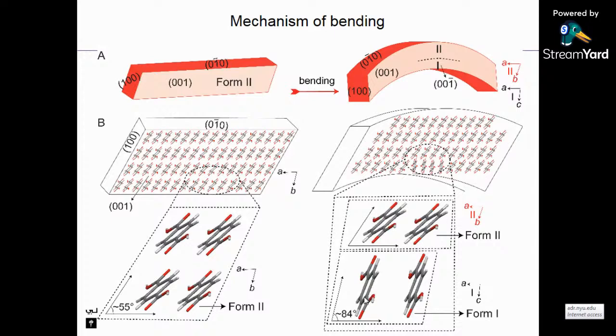So due to this existence of polymorphs at the bent stage, and also when you look at the mechanical properties, form 2 has higher hardness than form 1, and form 1 is much softer in nature when compared with form 2. Due to these properties, the bent shaped crystal stays in that bent shape.